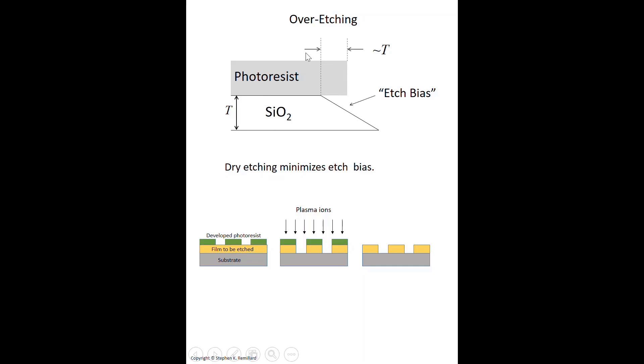If you cover your silicon dioxide with photoresist, what you want is to be left with a silicon oxide block that has a wall right here. But what you get is something else. HF might eat away underneath it, and that's referred to as etch bias, which is actually a quantified amount. How much etch bias you have is this big T. It's how much underneath the photoresist you etched. It's important because what you end up with then is a line that's narrower than what you designed for. That can be taken into account if you know what the etch bias will be, and you can actually go ahead and make your mask slightly wider to get that. But in dry etching, all that is avoided, and it's still undesirable because that's not the shape you want your edge wall to be. You want a vertical wall.